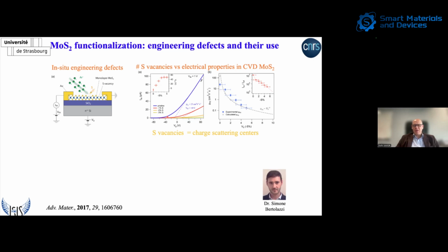Now, this might not be enough. You, as a chemist, might like to have more. And so how can you create more? There are a number of ways to create more defects on the basal plane of molybdenum disulfide and other transition metal dichalcogenides. For example, you can irradiate with the ion beam of the X-ray photoelectron spectroscopy, like we did here with the argon beam. You can anneal. You can use electrochemical stimuli. You can use photostimuli like lasers. So there are a number of different manners to create defects.